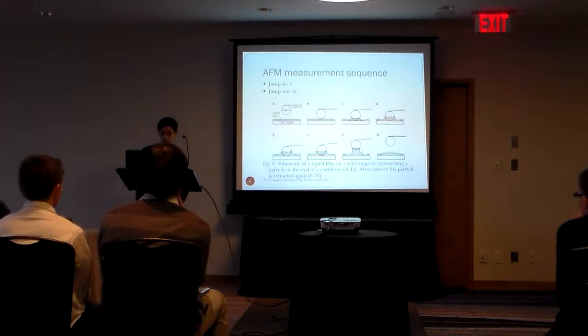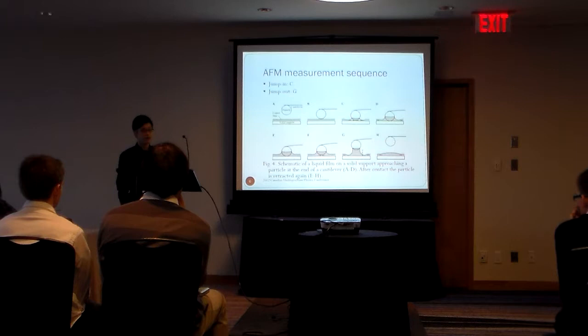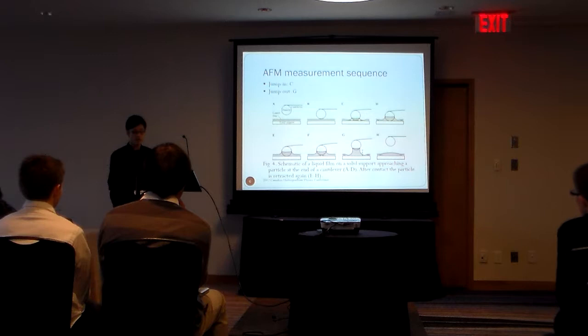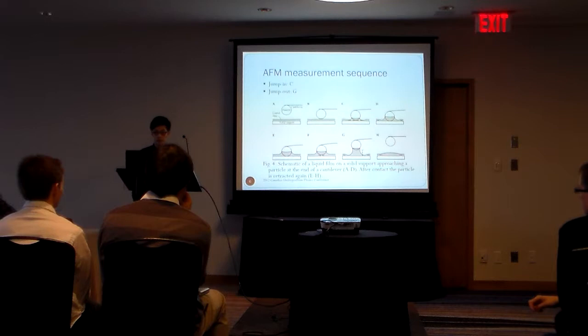This measurement sequence is best summarized with this diagram. As the colloidal probe approaches and retracts from the liquid film, there are two very important events: the first is the jump in at C, and the second is the jump out. As the colloidal probe approaches the film, a meniscus forms even before the particle contacts the film, caused by short-range forces such as van der Waals, and also depending on the viscoelasticity and non-Newtonian properties of the film. As the probe retracts, another meniscus is stretched, opposing the motion of the particle — this is caused by drag and hydrodynamic forces — and the meniscus thickness H depends on non-Newtonian properties of the fluid.